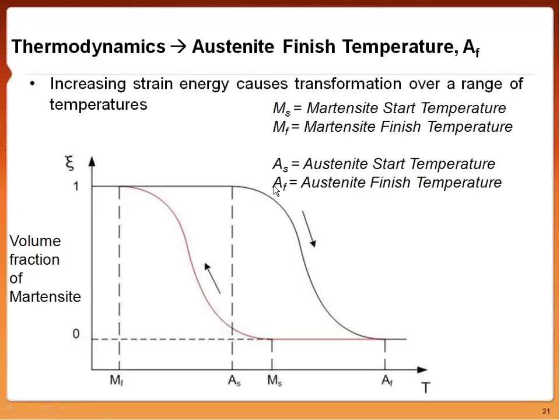And the same thing can be said of the heating curve, when we go from an austenite start temperature, where we're still at 0% volume fraction of martensite, and as we gradually heat the material back up, we go to 100% austenite, or the austenite finish temperature.